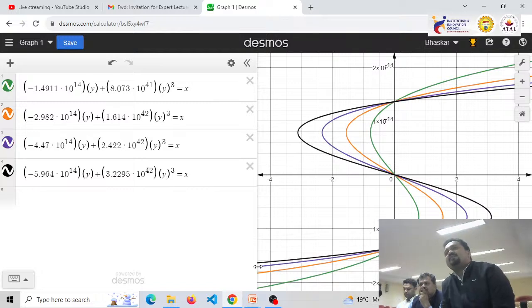So here I have restricted myself to the graph up to TFE equals 120 nanometer. There is a particular reason behind it, because after this I will be going for FE-DE heterostructure, and if I increase my thickness beyond 120 nanometer, because in the upcoming graphs I have taken the dielectric thickness as 1 nanometer, the hysteresis starts appearing in my characteristic. That's why I have stopped here at 120 nanometers.